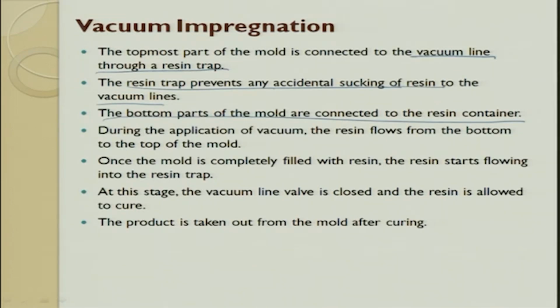During application of vacuum, the resin flows from the bottom. Resin can also flow from the top. If it flows from the top, there is a possibility of air getting trapped or some other defects coming into existence. So, we always suck from the bottom. So, the resin flows from the bottom to the top. Once the mold is completely filled, the resin starts flowing into the resin trap. At this stage, the vacuum line valve is closed and the resin is allowed to cure.